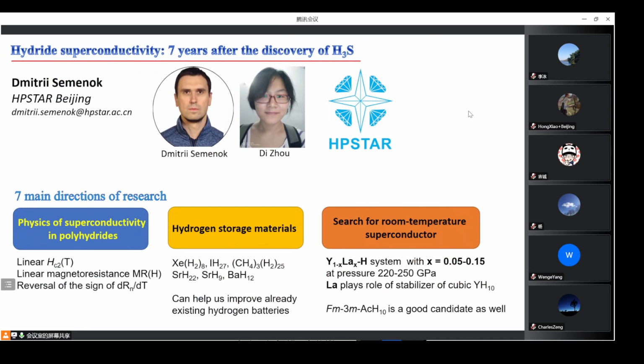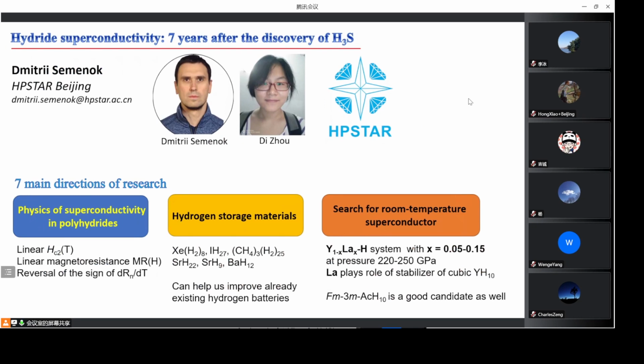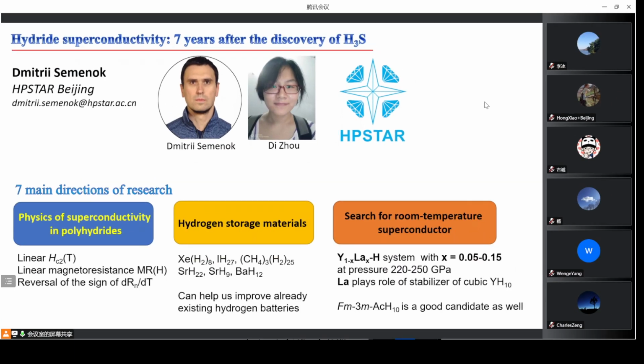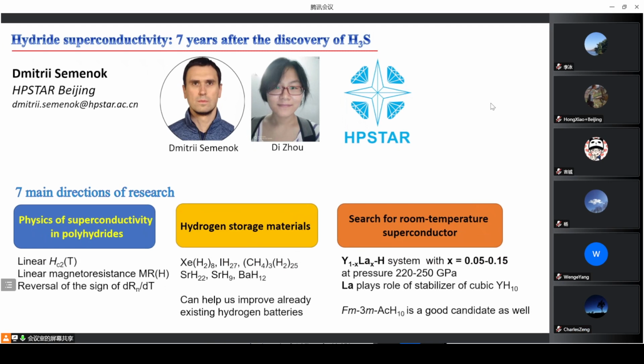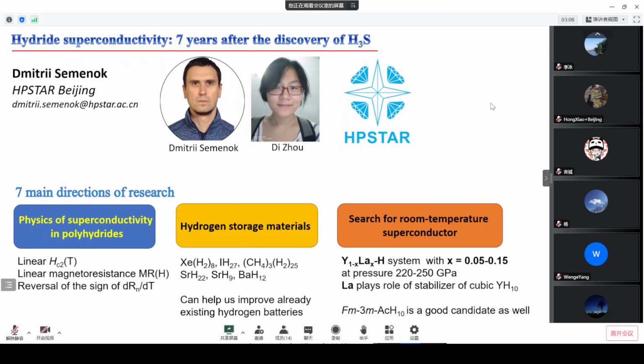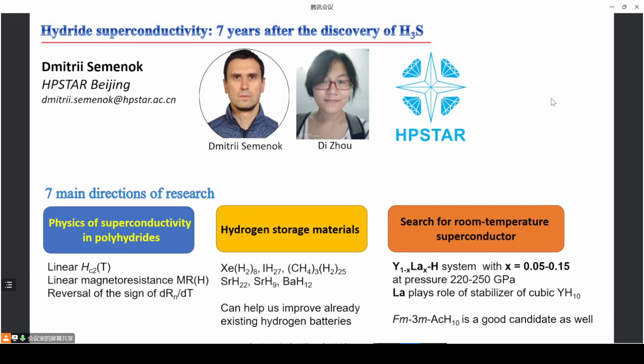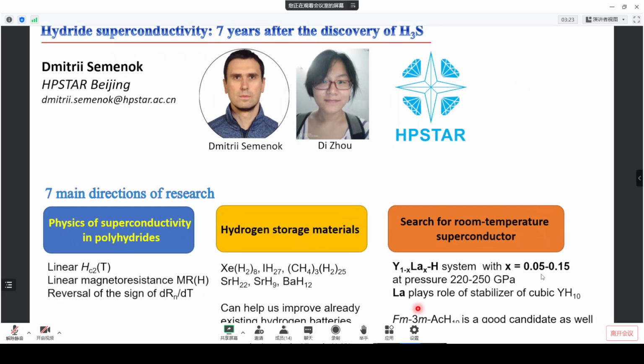And one of the promising ways to find the room temperature superconductor is probably doping of the yttrium hydrogen system. If we introduce, say, 5–15% of lanthanum inside of yttrium H10, maybe it's possible to stabilize a cubic modification at a little bit elevated pressure, such as 220–250 GPa. Another option is to synthesize cubic actinium H10.